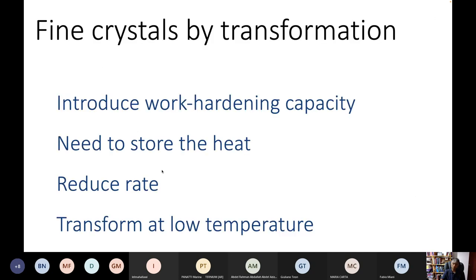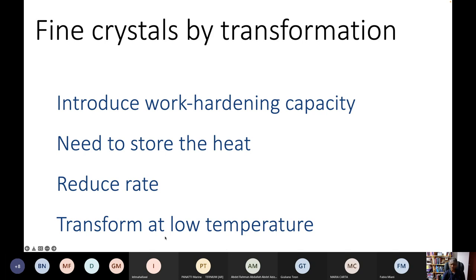If you want to achieve bulk nanostructured steel, we've got to introduce a mechanism for work hardening inside our material. You also need to store the heat of transformation inside the material. You want a slow rate of transformation because then the heat can diffuse away. Transforming at a low temperature is good for getting a fine structure by phase transformation. So we don't want to use cold deformation to produce a nanostructure — we want to generate the structure by phase transformation, and that way we can make samples which are large in all three dimensions.